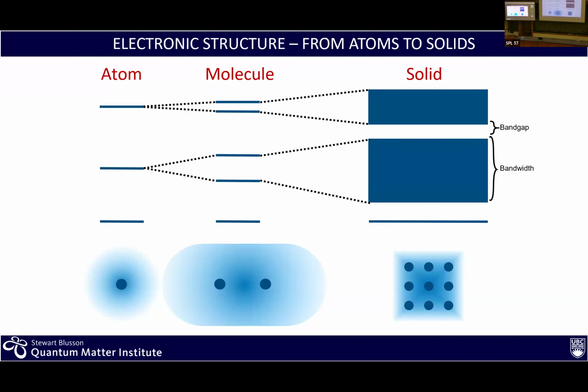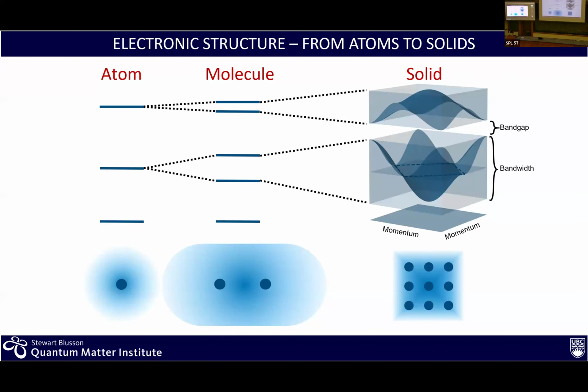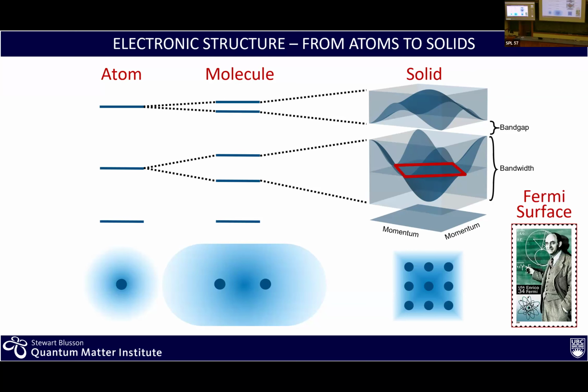And so now we start looking at how to describe the system, and that's where people like me or Eduardo come in, really looking at the detail of the electronic structure. In an atom, you have discrete levels. As you start going towards the molecule, you form some hybridization and some molecular levels. In the solid, of course, the hybridization is strong, and these levels evolve into bands. And these bands now come with a new quantum number, which is momentum. It's basically the directional propagation of the electron, and the relation between the directional propagation and the energy of the electron is your band dispersion, which really is critical here, because you're going to fill this energy diagram with electrons up to the point when you run out of electrons. And this is called the Fermi surface. So when we talk about superconductivity, everything has to do with the interaction of the electrons at the Fermi surface. Those are the ones that will form the Cooper pairs and will give you superconductivity.